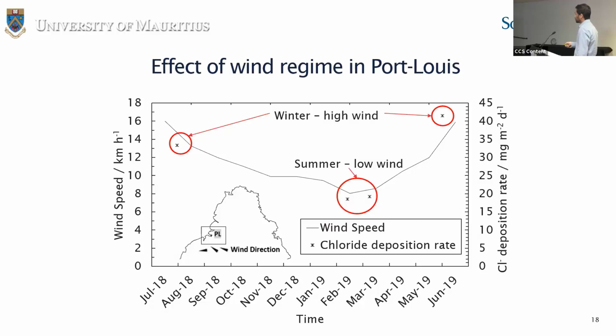The chloride measurements carried out during winter coincide with the high wind conditions and the values are high. The chloride deposition rate measurements carried out in summer coincide with the low wind conditions and the values are low. This implies that chloride deposition rate increases with wind speed.